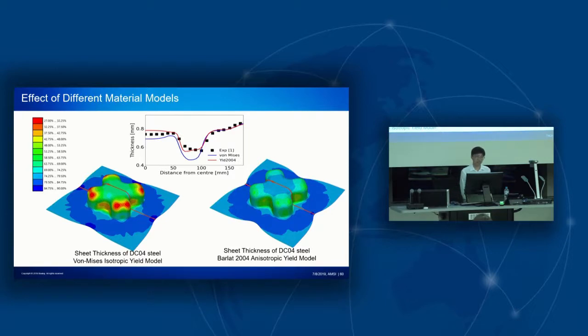Here I just show some results and explain why we need to adopt a proper material model in sheet metal simulation. Here is just a simple deep draw test. So we are just trying to simulate a DC04 steel, which has been tested and has very high material anisotropy behavior. The result at the top line is from the one basic isotropy yield criteria, which you can see provides a very inaccurate thickness distribution. And this will result in extra iteration and waste, as well as costs in the manufacturing process.